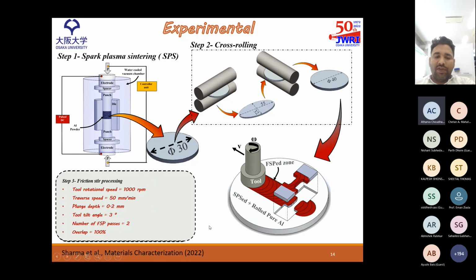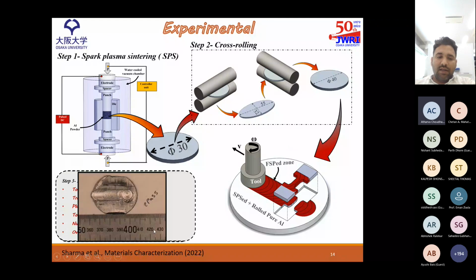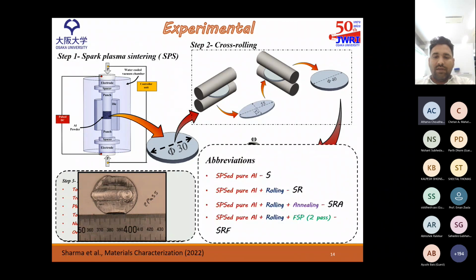So we have done the FSP with two passes. However, we are still optimizing this process, and we are further increasing the number of passes to 3 or 4, or somewhere we can obtain the optimized properties. And we have done it with 100% overlap. And this is the final product that we have obtained. This is a billet, and we have done a nice friction stir processing over it with a very fine dimensional tolerance.